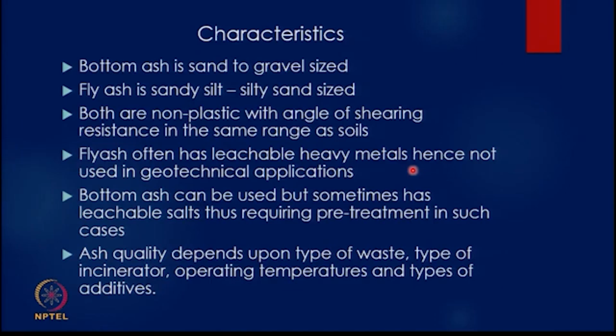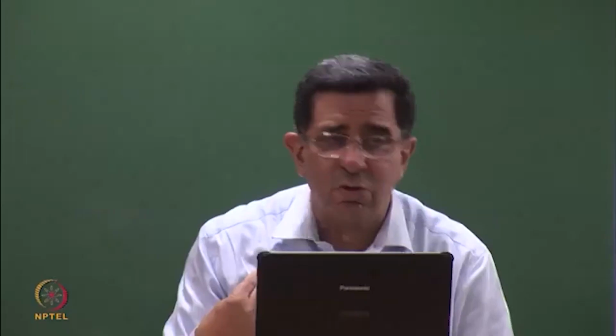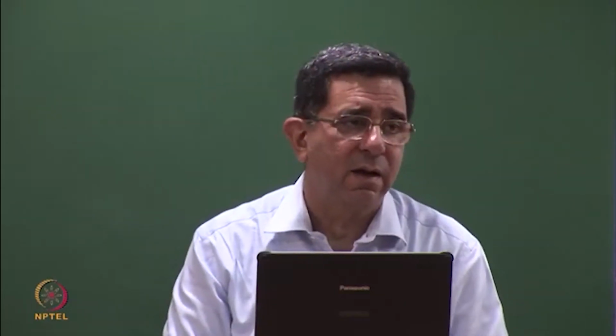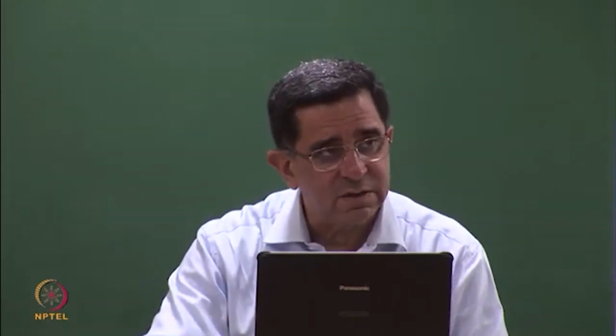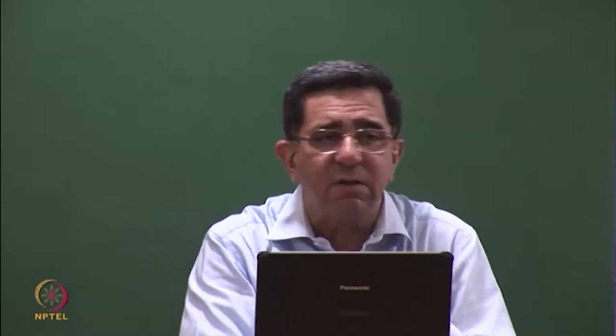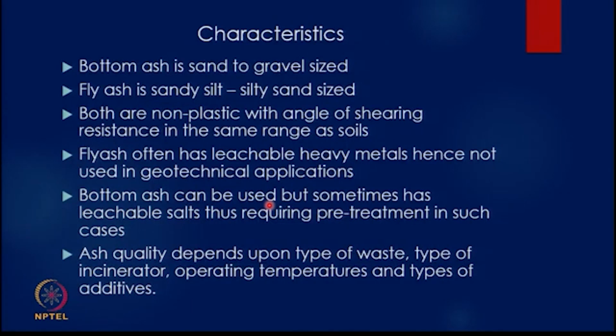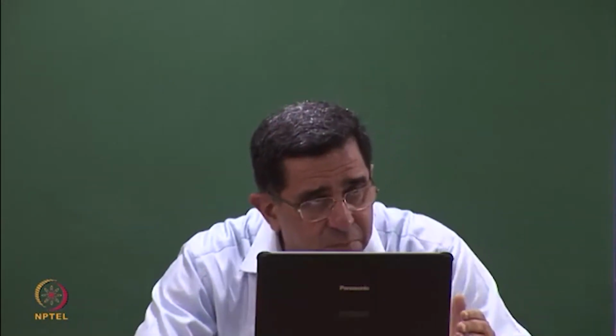In coal ash, it is still not 100% clear that all fly ashes have leachable heavy metals, though America is now saying that from the ash ponds some unusual heavy metals are leaching out. But here in MSW ash, in the fly ash, which is a low percentage, the metals get volatilized in the furnace, they go with the flue gases, and when the flue gases are caught with the ash, they deposit themselves on the fly ash. Bottom ash can be used in geotechnical applications, but sometimes has leachable salts, and therefore you may need some treatment or dosing of the bottom ash for earthworks. But in the bulk of the cases, bottom ash is reusable with some nominal pre-treatment.